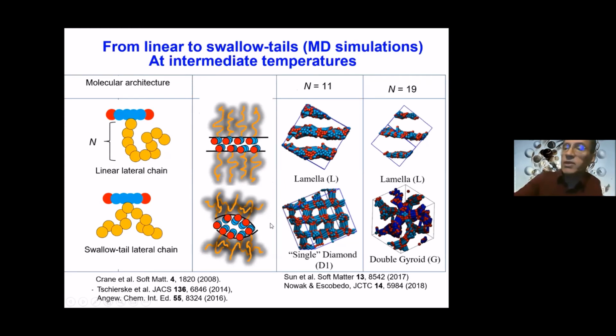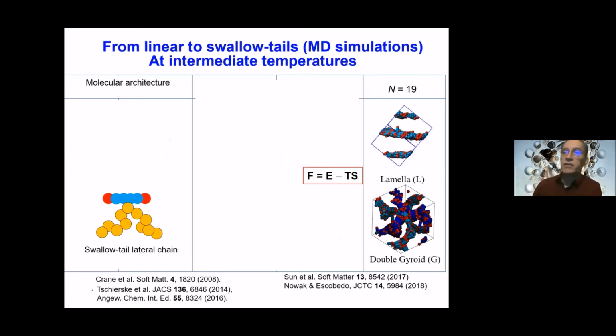But to see things more quantitatively, you have to, of course, measure the free energy. And I'm going to show you an example where we look at this case, this system, for this n value that can form the L phase or the G phase. What we find is that the G phase at intermediate temperatures is the more stable. But when you look at the energetics, we find that the lamellar phase has the lowest energy. So that should be energetically favorable. That makes sense because, the interface being flat, you have less interfacial penalty. But we found that the G phase has the lower free energy.